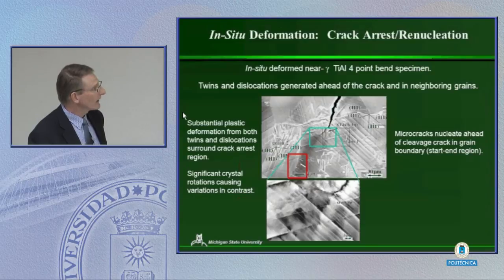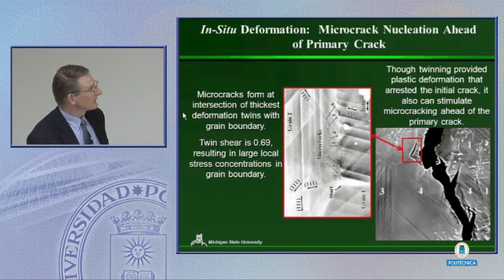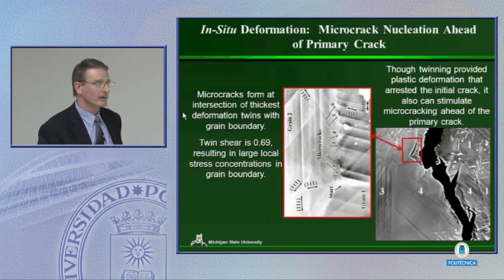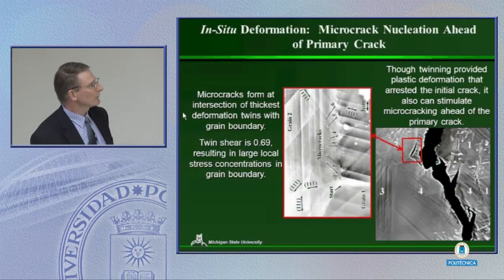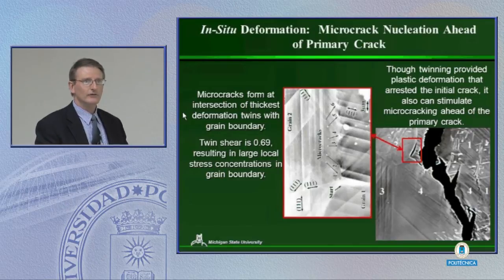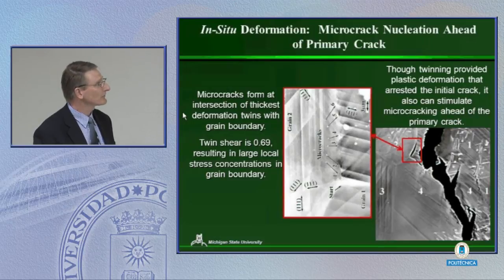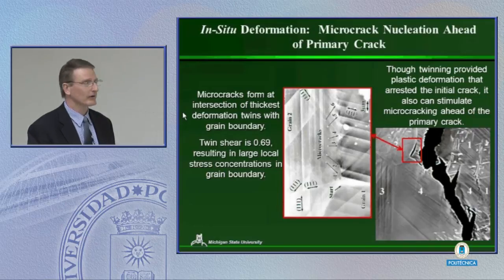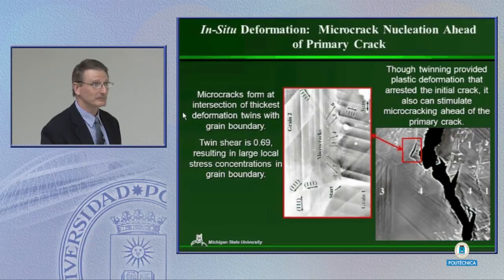What I want to do is concentrate on what's going on up in this little zone up here, which you'll see in the next slide. So this zone is right here. And what we see is we have a bunch of twins here. And right at the tip of some of these twins, we have some very small microcracks that are nucleating. At first blush, we looked at this and said, well, the twins are running into the boundary and that's creating a crack. But in fact, what's happening here, which I think is maybe even more interesting, is that these twins are actually nucleating here, and they end up terminating. You can see some here terminate as they move out from that boundary. So they nucleate here, but when these twins nucleate, they leave cracks behind, which is kind of interesting.